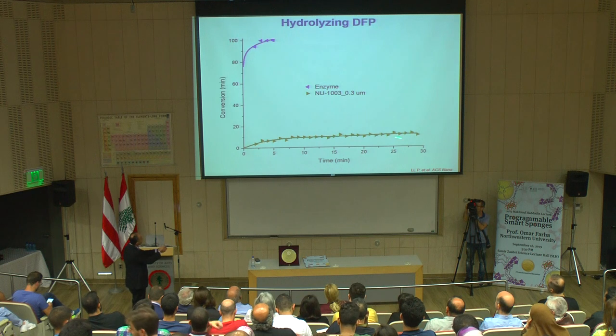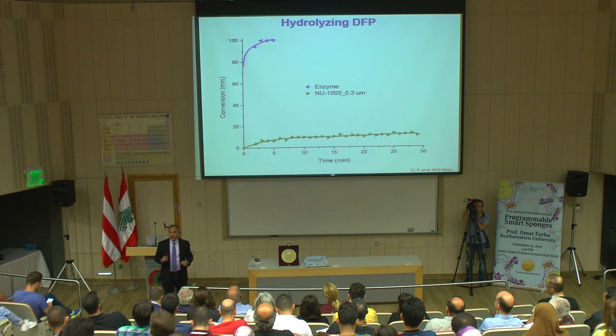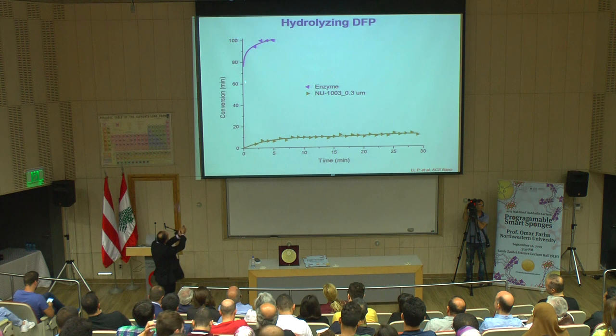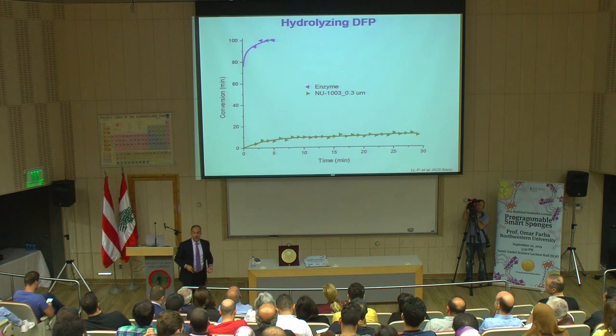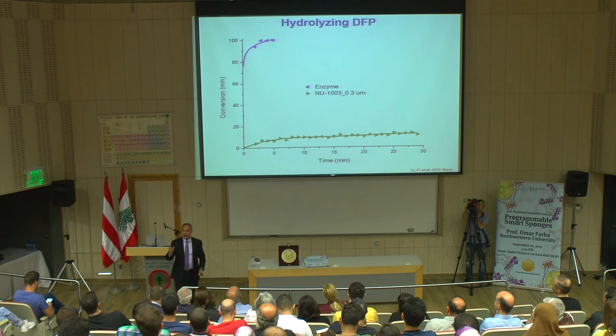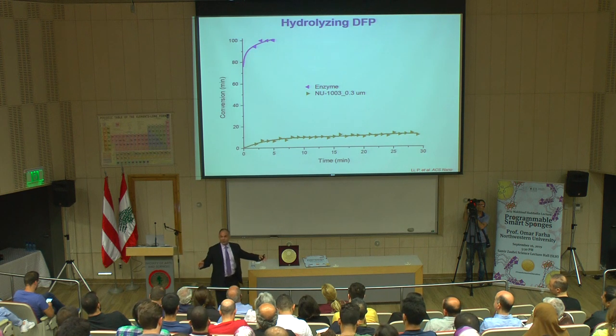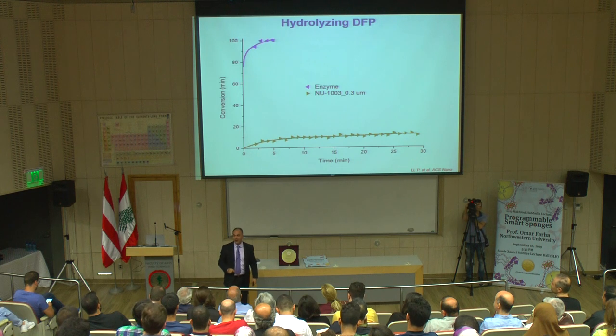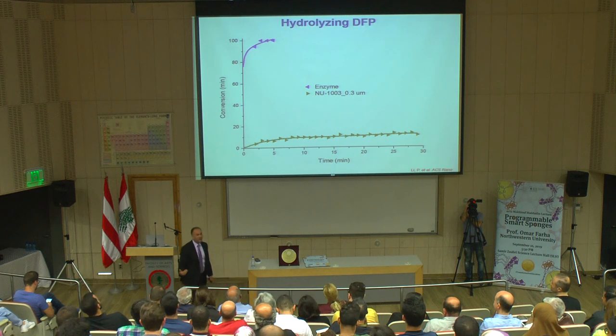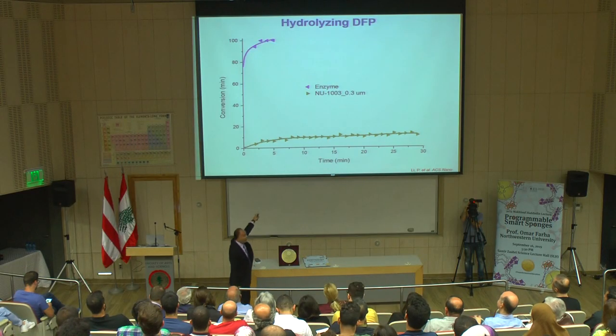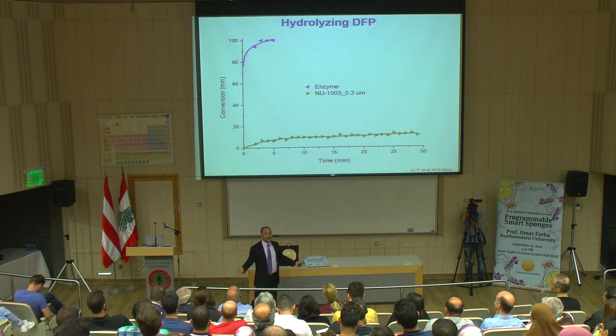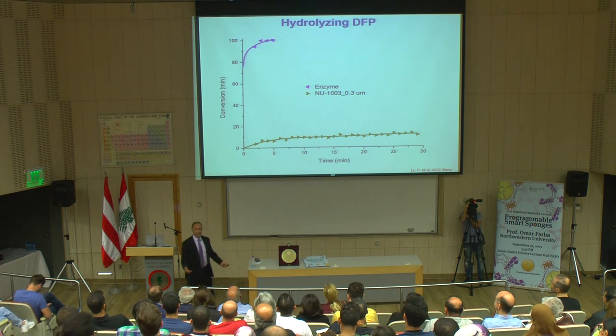Now let's test the catalysis. One thing I wanted you to pay attention to, the first example of this particular enzyme I showed you, that we got from our collaborator, plateaued around 80%. This one is a more active batch. In the 6 months it took us to make larger channels and get this distribution of particles, they were tweaking the active site of that enzyme to make it an even more potent enzyme. Now our job is even harder. We're not going to compete against the enzyme that plateaued at 80%. We have to compete against that, as soon as you take the NMR of almost the first point, it's like 95% done. So that's now the challenge we had to face.